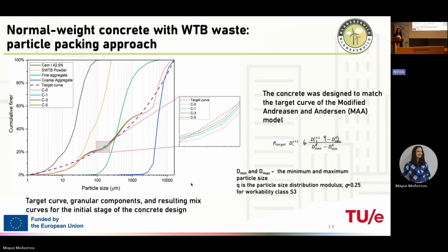So here in our group, the building materials group at TU/e, we use the particle packing approach a lot. And here we use it also to make material like concrete more dense, because the density of wind turbine blade waste is significantly lower than other components like cement and aggregates. Second, as you see, and I repeated it several times, the waste is really heterogeneous. So we also have challenges applying this particle packing approach, because it's really not granular material. For fibers and flakes it was challenging, but still we managed to optimize the known model, the modified Andreasen and Andersen model, to this target curve.